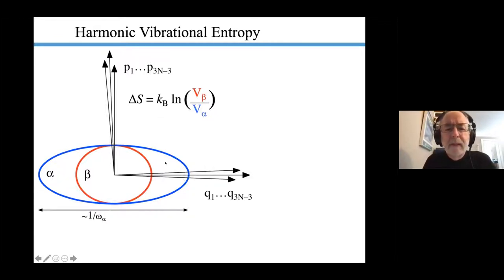So these are two crystals which might have different forces between them, but the same atoms. So the kinetic energies are still kT for all of the atoms, and we don't vary along the momentum position. So we need to get a volume in what we call state space or phase space, which depends on all of these exploration ranges of the positional coordinates from the vibrations of the atoms. And the difference in vibrational entropy between the beta crystal structure and alpha would be the difference between the two logs, or the ratio of the volumes that we explore.